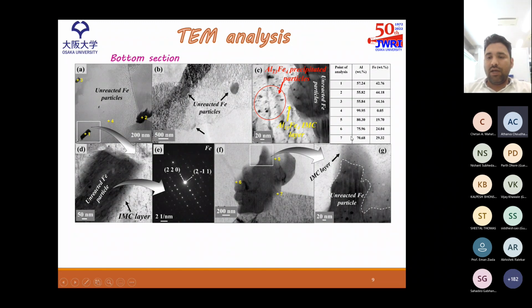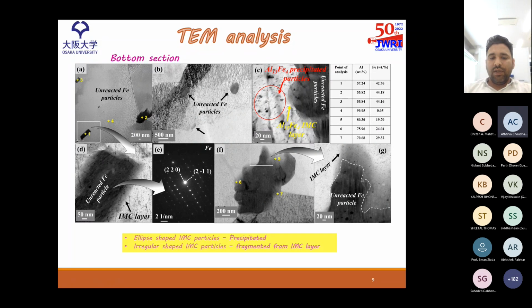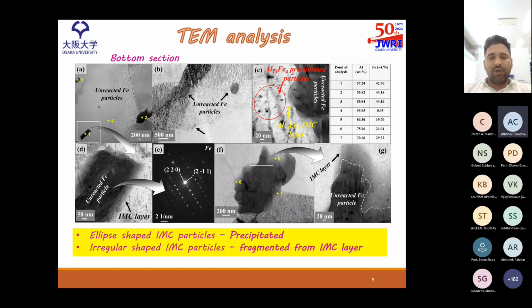However, we have observed a layer also. This is a diffusion layer or the IMC layer which is formed around the Fe particles. But this layer has a high thickness because in the bottom part the stirring action is also very less. So that's why it is not broken and not fragmented, and it remains intact with the particle. Here we can see some of the IMC particles which are precipitated and formed in the matrix. So here also two types of morphology are obtained. One is the irregular one and another one is the ellipse-shaped morphology.